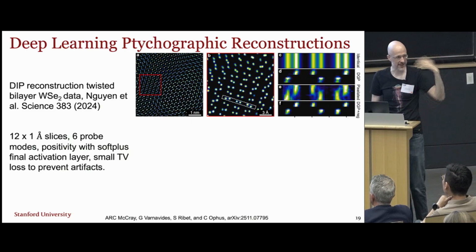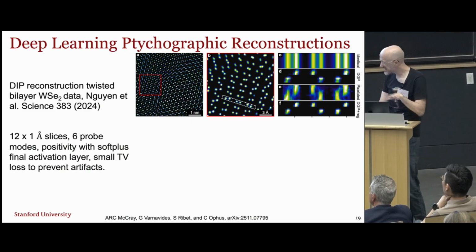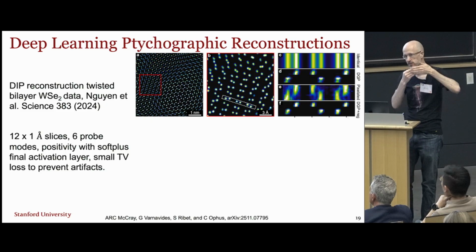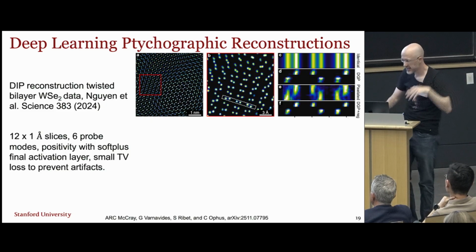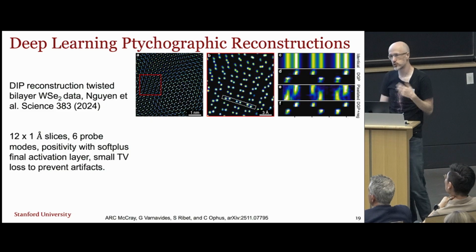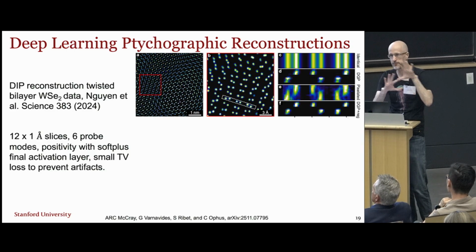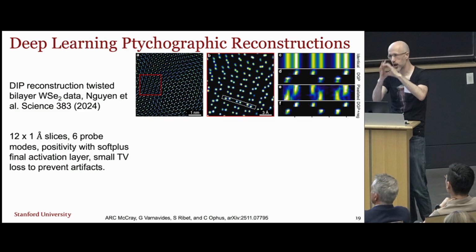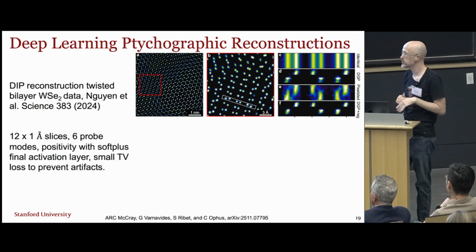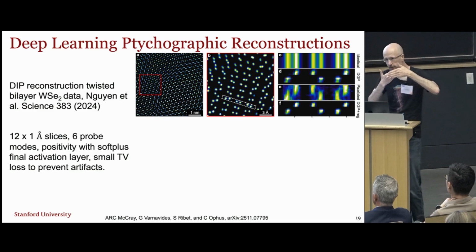OK, so looking at Pinshane's data here, excellent data quality. And this is a really good test of the theoretical resolution along the beam, right? Because in ptychography, if you do the calculation for electron ptychography, you'll see we can get half an angstrom in plane pretty easily. If we image outside of the numerical aperture, right, often you can get down to about 0.2, even 0.17 angstroms. That's what the Cornell groups have shown here. But along the beam direction, it's much worse resolution because it's very ill-conditioned.